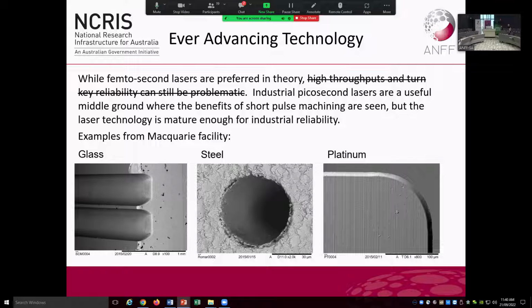And in answer to some of the questions, like how can you do maskless etching with a laser, you can get away with prototyping, but you're never going to get the surface morphology as beautiful as you can with the DRIE process, for example. So what we've done for University of South Australia, in some of the projects that happen here, is that we will often do the first glass prototype, because we can machine borofloat glass reasonably well. But we're still going to leave behind a 0.5 micron roughness finish, which is not real nice when you're trying to look through it with a microscope. But if all you're after are some microfluidic channels, it's just as quick to get us to machine them up for the first couple, rather than go through the process of making up the lithography mask, doing lithography and getting it etched.